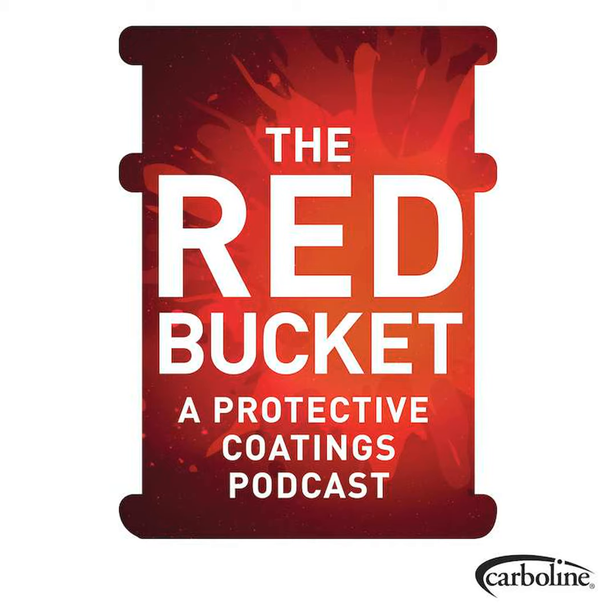And then it brings all those uglies, calcium salts, whatever is left in the concrete, because concrete's not a fully reacted material. In fact, some civil engineers will state that it still reacts as much as 25, 30 years later. Wow. And so with that in mind, we have those physical properties going on, and it's difficult for a coating. Typically, if it's 3,000 PSI Portland cement, your surface tensile strength is about a 10% value of 300. And so that's how we rate coatings if it's acceptable for concrete, because if you put an epoxy coating on and it has far greater properties and you do a pull test, the concrete will fail wherever its weakest plane is.